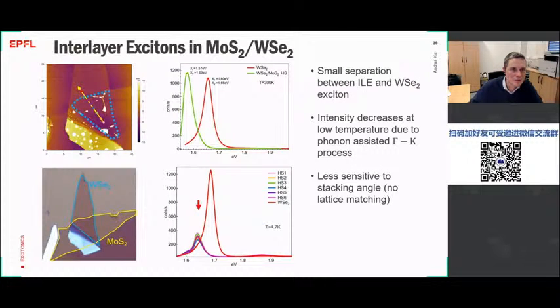And then finally, once you have these nice heterostructures, you can look at photoluminescence, and then you can see how once you have a heterostructure, your photoluminescence peak goes down in energy, and the intralayer exciton peaks are suppressed, and this then tells you that you have a good and highly efficient formation of interlayer excitons inside your structure.